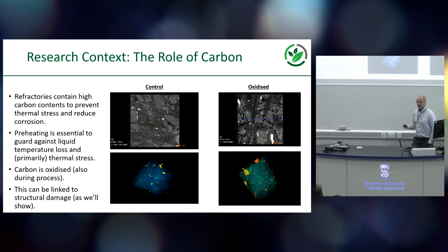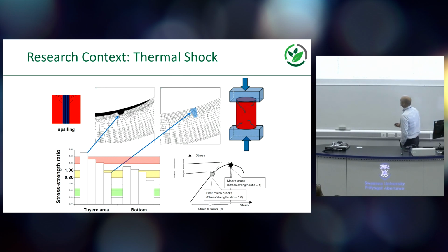Now the carbon's in there for a very good reason, and that is that one of the main damage mechanisms of refractories is thermal shock. So they don't just have to be good at insulating from the perspective of temperature, they also have to be very resistant. And why is that? It's because one of the main reasons that you will actually stop a steel making process is because your refractory lining is knackered. We spend an awful lot of money trying to ensure the continuity of the process, and it can have a significant impact on the bottom line of the business.